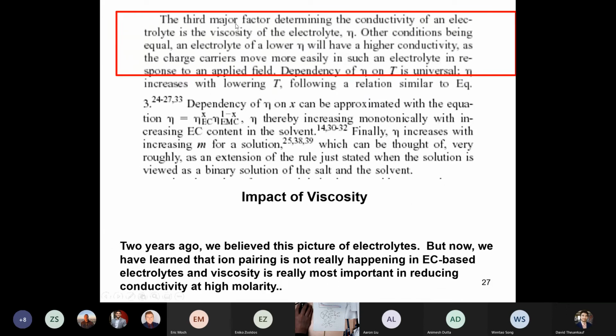And then they say the third major factor determining the conductivity of the electrolyte is the viscosity, right? Other conditions being equal, an electrolyte of lower viscosity will have a higher conductivity as the charge carriers move more easily in such an electrolyte in response to an applied field. Okay, and this is fully true.